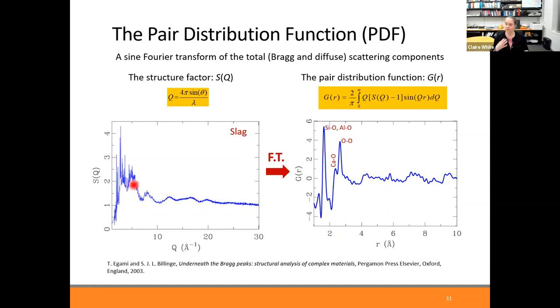And so what's shown over here is a sample that has both diffuse scattering, so scattering from an amorphous component in the material, and also these spikes are the Bragg peaks, the crystalline contributions. So you're Fourier transforming both the disordered component, if it's present, and also if there's crystalline contributions, you're Fourier transforming that, and you're ending up with your pair distribution function over here, which is a histogram of all atom-atom distances in your material.